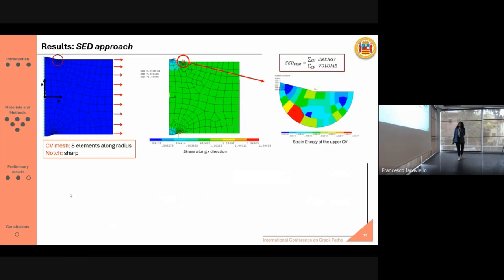Concerning the results for the finite element analysis, in particular the SED approach, here we can see a contour plot of the stress along the y direction, that is the vertical one. And here we have a zoom in of the upper contour volume, and this is a contour plot of the strain energy in that volume, dividing the total strain energy by the total element volume. We have the strain energy density itself.